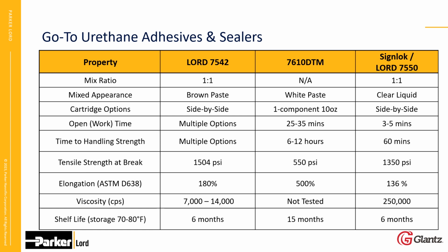You can compare it to a tube of caulking or silicone from a big box store. Generally, their adhesion rate is about 100 to 150 pounds per square inch, where ours is, as you can see in the middle there, 550 psi. Extremely strong, extremely heavy duty. It also has a longer shelf life as well. We'll get into this in more detail in the next slide.